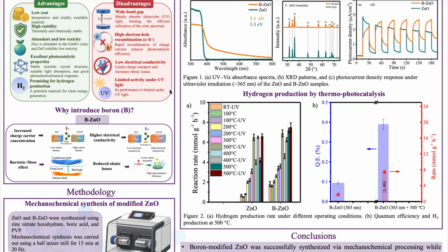Why modify ZnO with boron? To overcome these limitations, we decided to incorporate boron into zinc oxide, as illustrated in the poster. Boron incorporation increases the concentration of charge carriers through the Burstein-Moss effect. This enhances the electrical conductivity of the material, reduces ohmic resistance, and promotes a more efficient separation of photogenerated electron hole pairs. Consequently, a higher photocatalytic efficiency and enhanced hydrogen production can be expected.